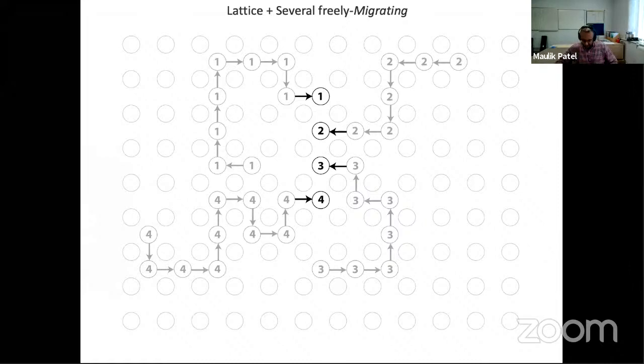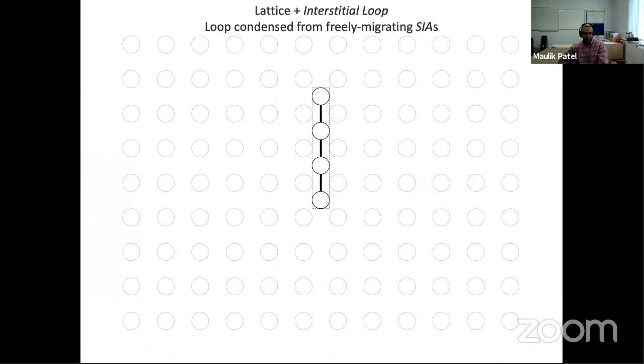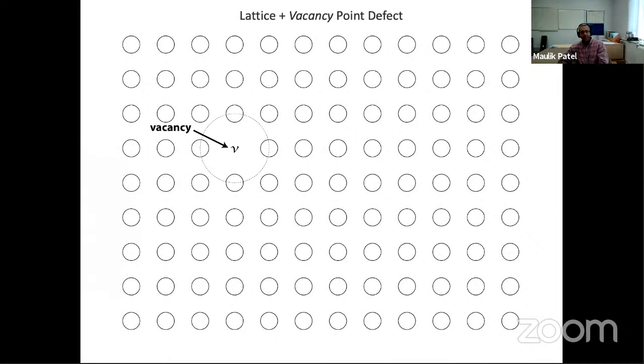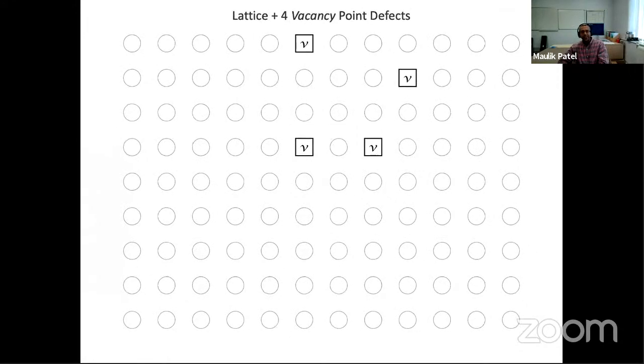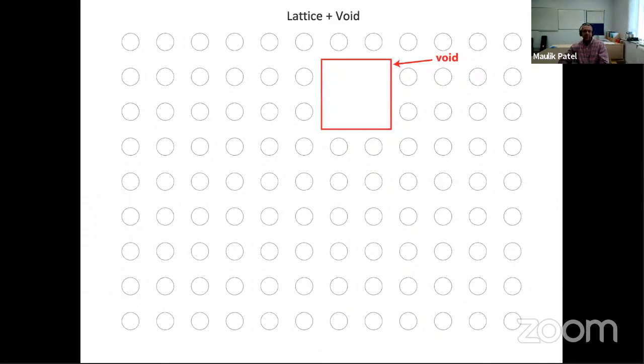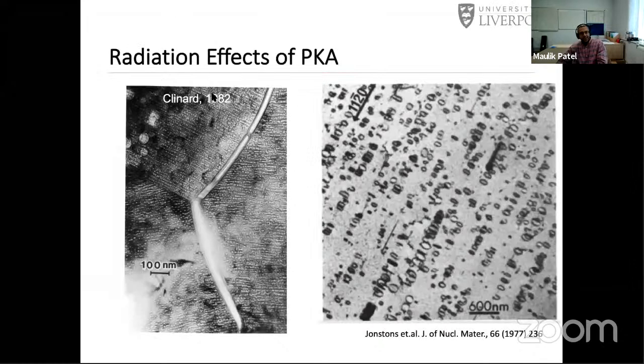And then if you heat the material, which is the right conditions available in a nuclear reactor, right? So you add heat to it, all these interstitials can move. Interstitial mobility is pretty fast, faster than the other component of that defect, which is a vacancy. When they move and agglomerate, they form something called an extended defect, which is a dislocation loop. And you're left with a vacancy. Again, over time, these vacancies move, and you are left with an empty space in the lattice, which is called a void.